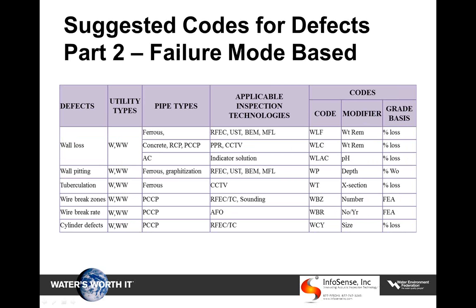Wall loss is a failure mode in gravity lines, but it's not nearly rigorous enough for us to really determine what the condition of a pressure main is. So here we've expanded the wall loss category and made it much more rigorous based on actual percent of wall loss and wall remaining. And also wall pitting, tuberculation, particularly for water mains, and for pre-stressed concrete cylinder pipe, we're adding wire break zones, wire break rates, and we can even look at cylinder defects.